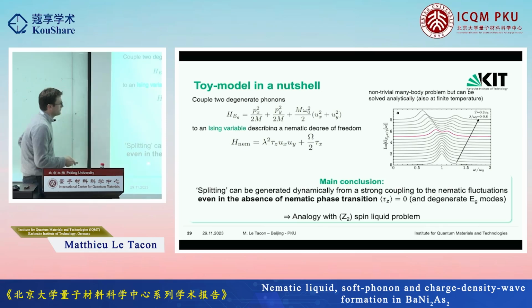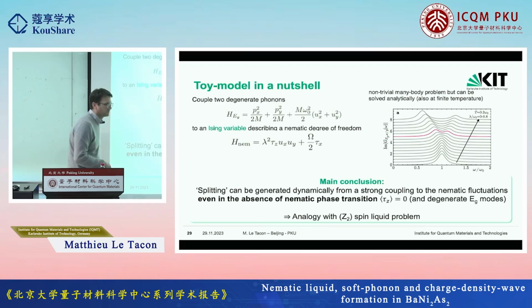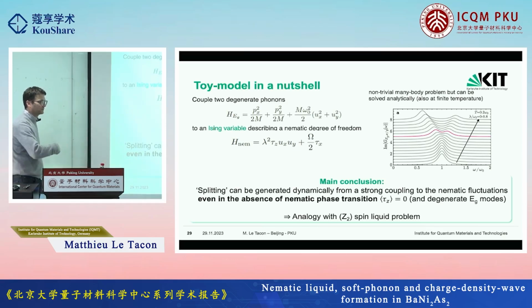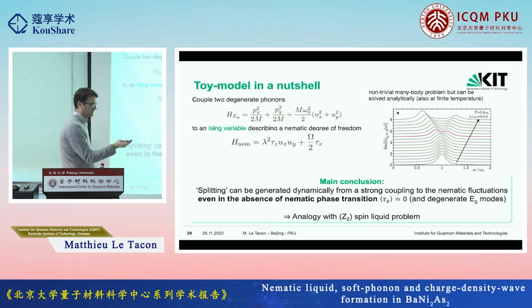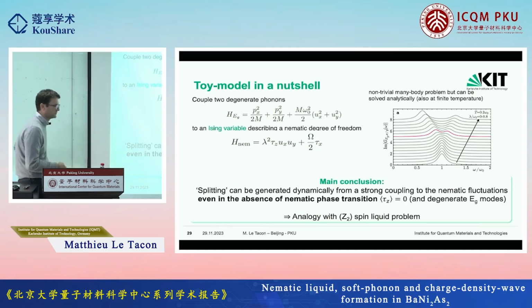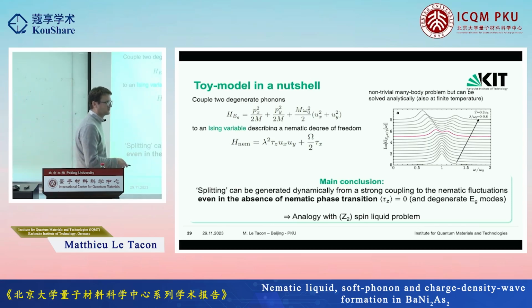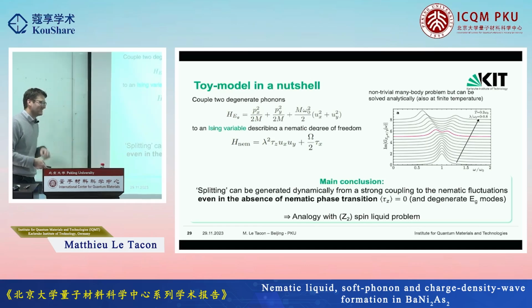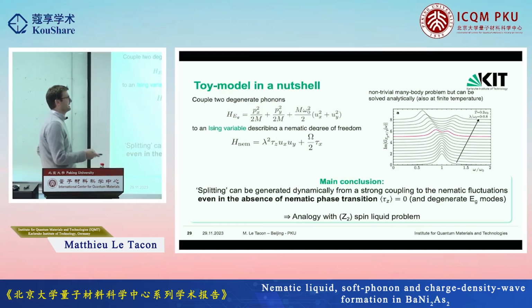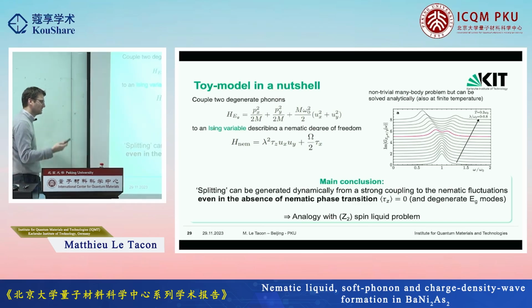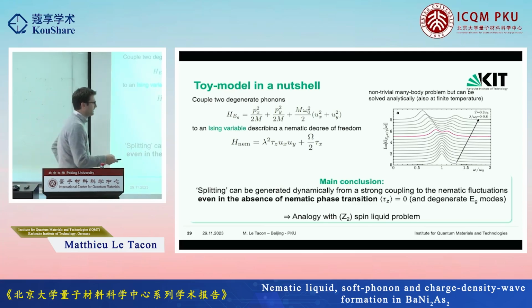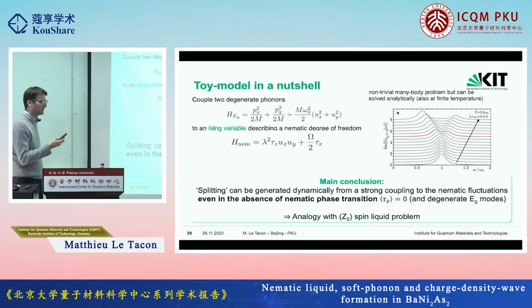Now, what is also very nice is that from a formal point of view, this has a strong analogy with the spin liquid problem, because you typically have a strong fluctuation between degenerate configurations without long-range order. And that excited Jörg quite a lot. But I have to say, not the editor much. So we had to soften some of the things. But in principle, in the regime where you can bring this kind of fluctuation down to the lowest temperature, you can end up in a system where you do have a quantum nematic liquid, and then you could expect some funny physics to occur.